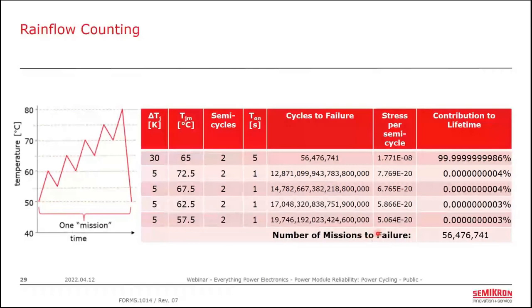So this value at the end here represents the cumulative stress of all of these cycles together. Now, some of you have maybe already noticed that in this particular example, the number of cycles to failure for the entire mission is pretty close, or in this case, exactly the same as the number of cycles to failure due to this major delta T of 30 Kelvin shown right here. And that's exactly the point of what I'm trying to show you here, is that when you have complex temperature profiles, you can very often ignore smaller variations or take a lower resolution of a data set that focuses only on major temperature swings. So you can simplify your data set and then you can simplify your calculation effort.